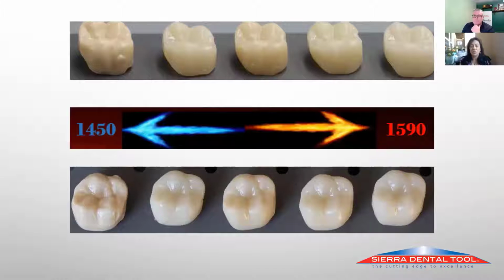All right, so these crowns are all the same. The top and bottom are the same. On the far left, we have severely underfired, and all the way to the right, we have overfired. So this particular zirconia is a very commonly used, well-known zirconia. It's supposed to be sintered at 1550 Celsius. So the first crown was sintered at 1450, and I did this on purpose so that I would have examples, and so people can see what really happens.